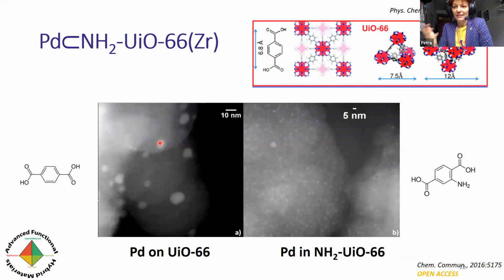So we have previously, for completely different purposes, looked at the system in which we use the UiO-66 topology. So this is what it looks like. It's one of the archetypal metal organic framework topologies with zirconia-like clusters interconnected by terephthalic acid linkers. And we noticed that when we use the aminoterephthalate linker, we managed to confine and grow palladium nanoclusters inside the pores of the framework.